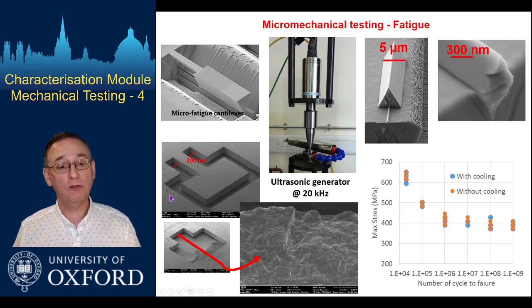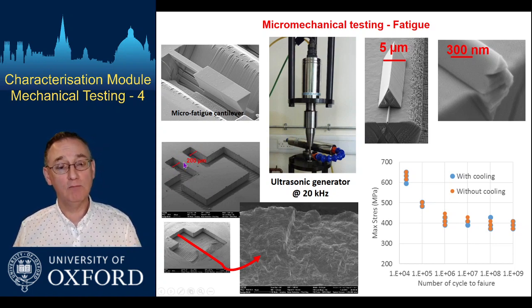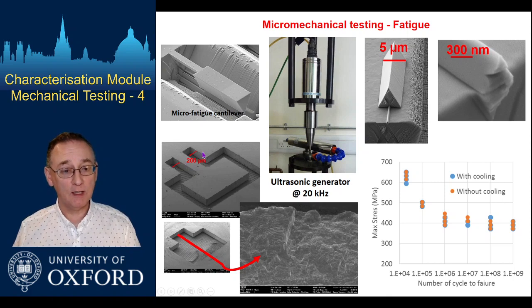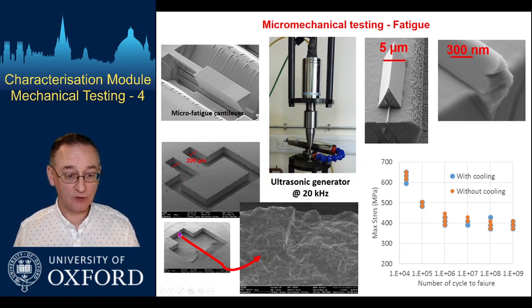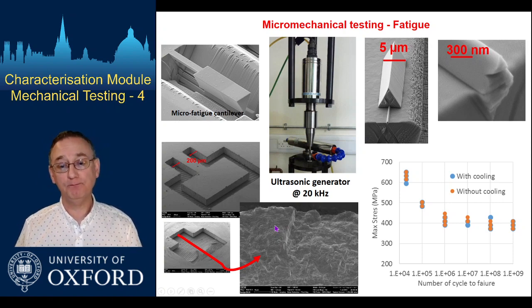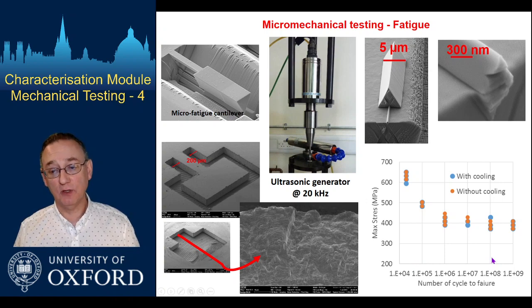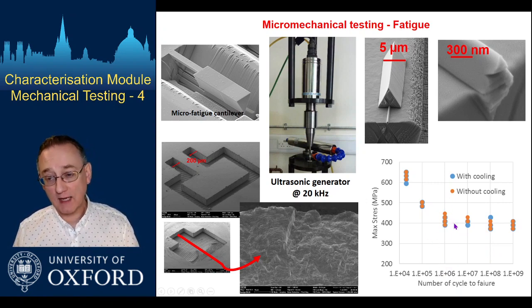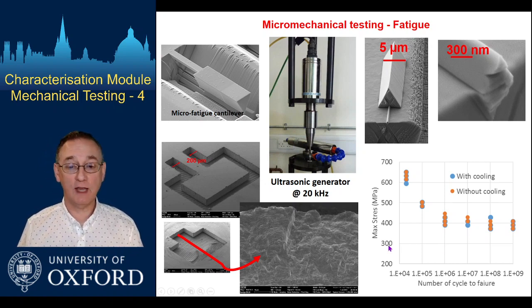Moving to slightly larger structures, if you use a thin foil and cut through with a laser, you can generate structures a few hundred microns across with patches of microstructure to examine. This is in stainless steel. The large section acts as a mass on this spring, vibrating at 20 kilohertz, so you can reach very large numbers of cycles and eventually the sample fails. After testing, you can see the fracture surface with striations typical of fatigue. Looking at S-N data, 10 to the 6 cycles is about 50 seconds of testing, so you can carry out to gigacycles — which under conventional testing regimes is very difficult to achieve.